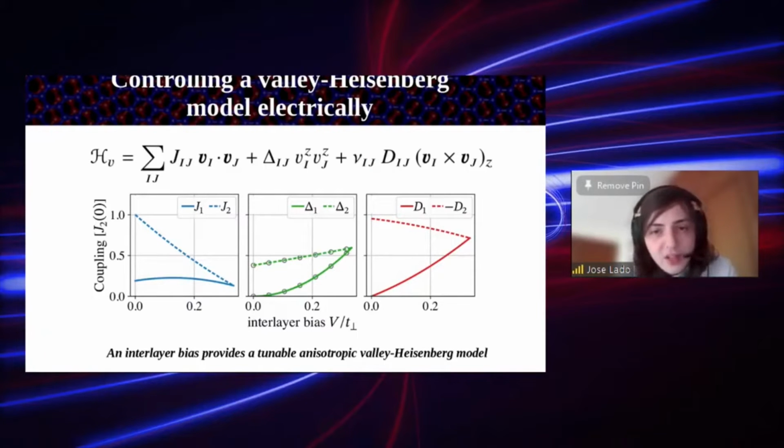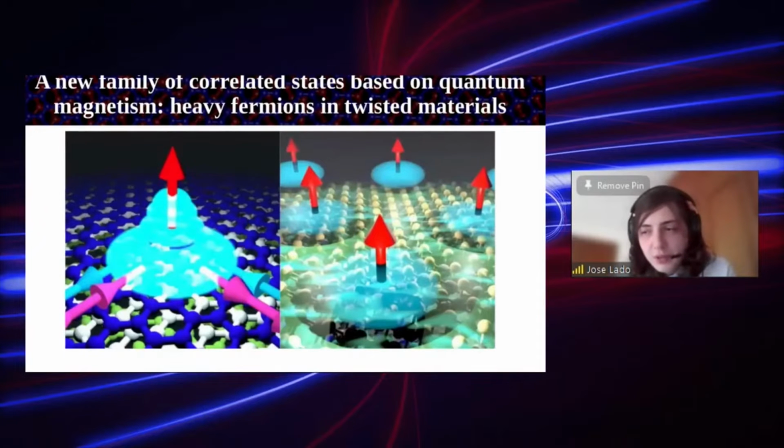So with this, you essentially know that with a twisted graphene bilayer encapsulated between ferromagnetic insulators, we can create a frustrated model with tunable interactions. And of course, solving a quantum spin liquid model is highly non-trivial, but the bottom line is that since you can control all the exchange constants here, one could look for this regime experimentally. So that was the first example of how we can exploit two-dimensional ferromagnets to create new states of matter.